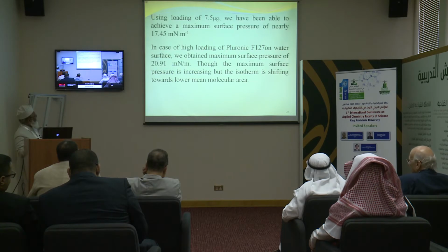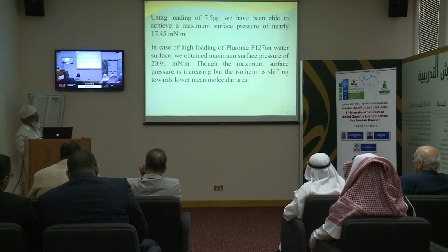With the high loading of Pluronic, we obtained the maximum surface pressure of 20.91. Though the maximum surface pressure is increasing, the isotherm is shifting towards lower mean molecular area.